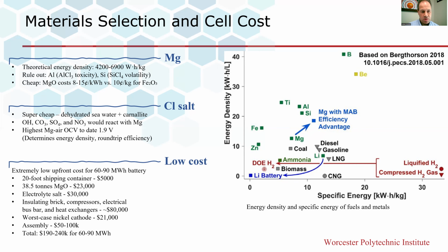Finally, very low cost. So the cost of the shipping container, the magnesium oxide, the electrolyte, other components, if we have to have a nickel cathode, assembly, even if assembly costs $50,000 to $100,000 per shipping container, we're looking at about $200,000 for 60 to 90 megawatt hours in a shipping container, which is about $3 to $5 per kilowatt hour upfront cost. So extremely low upfront cost for this battery. As I mentioned, it comes at the cost of lower round trip efficiency, somewhere around 50% round trip efficiency, and we will likely need to do some disassembly in order to recharge this battery. So it's very low upfront cost, somewhat higher operating cost for the battery.